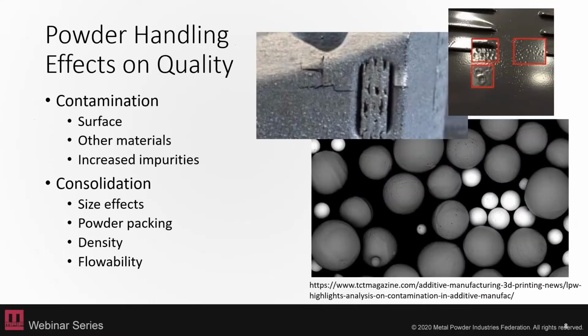So just kind of a summary here on the powder handling effects on quality. We want to make sure that you're handling carefully, because your quality will be affected by how you're producing and then handling and storing and shipping those powders. You're going to get contamination on the surface of those powders, whether that's additional reaction of the oxygen or carbon contamination on the surface, since carbon is just prevalent everywhere, or whether you're potentially getting other materials mixed in during your process and increasing the amount of impurities on those surfaces.